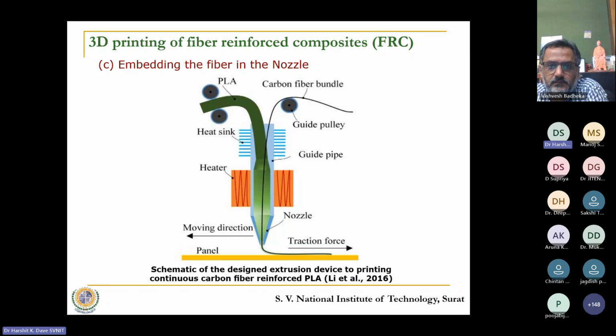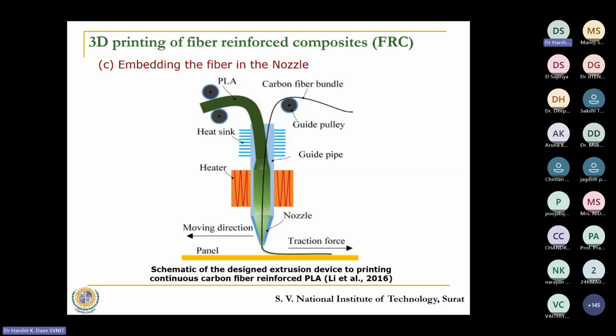but the part that is created would exhibit good tensile and bending strength. So of course here you do not require any specific change in the setup because there is a single nozzle. However, the problem that you face is that we have to maintain proper traction because the materials are totally opposite to each other. So that even distribution would take place only if their traction is maintained well. So the force with which the polymer would come and the fiber would come has to be ensured.